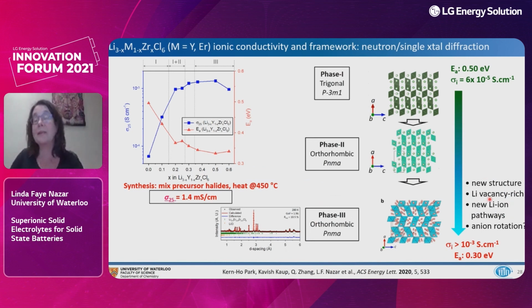It is certainly lithium vacancy rich by virtue of substituting a zirconium +4 for a yttrium +3. We also introduced new lithium-ion pathways in this material, and these are nicely described in the paper. I won't get into them now, but effectively there are pathways that have a lower activation energy, down to about 0.3 electron volts, compared to the starting material, which has an activation energy of 0.5 electron volts. So the conductivity, as you've seen in many of the other examples, increases by almost 2 orders of magnitude with this change in structure. And what we really do by changing the structure is we introduce a tetrahedral-octahedral pathway motif with this lower activation energy.